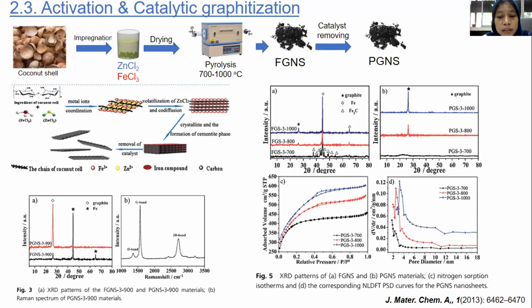The graphitic characteristic of PGNS, the sample after acid treatment, is further confirmed by Raman spectroscopy. This shows a higher G band compared to D band, and the presence of a 2D band. The increase of the carbonization temperature can result in an obvious improvement in crystallinity. Moreover, the BET surface area of the PGNS samples shows a high surface area for all samples, about 1,200 to 1,800 square meters per gram.